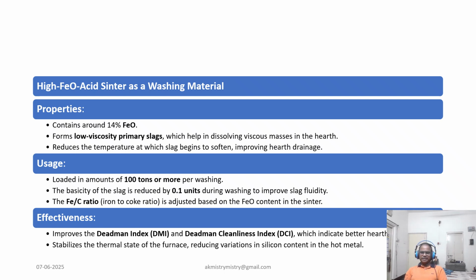temperature, aiding drainage. As far as uses are concerned, these are basically loaded up to 100 tons per wash, and slag basicity is thereby reduced by 0.1, which improves its fluidity. The Fe by C ratio is carefully adjusted, and the effectiveness lies with the improved drainage indexes like DMI and DCI, stabilized furnace temperatures, and silicon in hot metal.